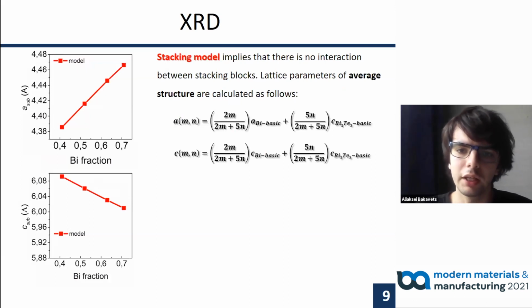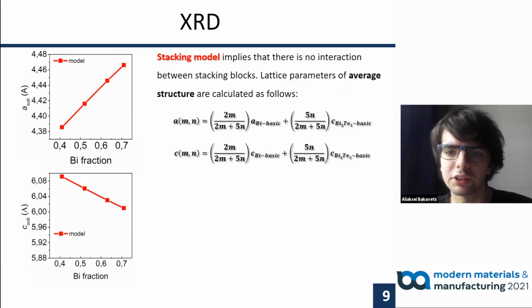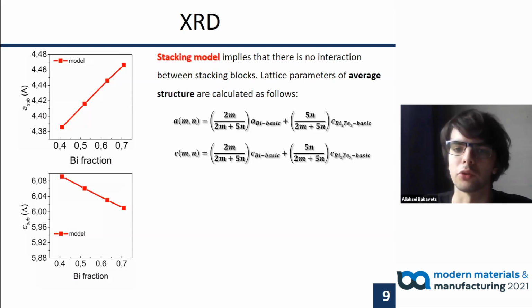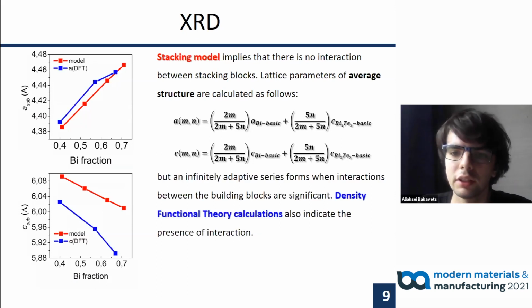In literature, the compounds of this series are described with the so-called stacking model. The stacking model assumes no interaction between stacking blocks. Lattice constant, according to the stacking model, can be calculated using the following formulas. On the other hand, structure optimization with density functional theory calculations has disclosed the interaction between stacking blocks, manifested especially in the shrinking of the c lattice parameter.